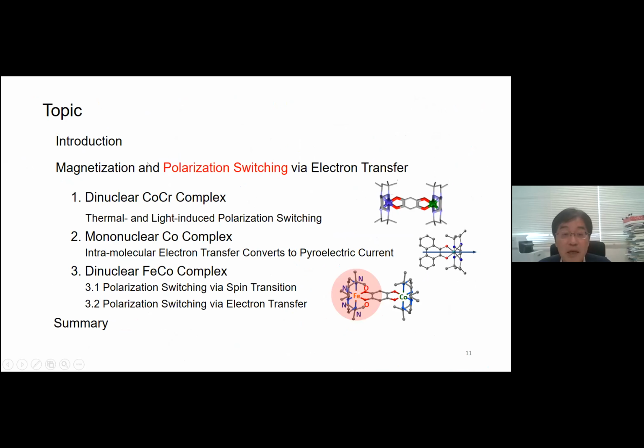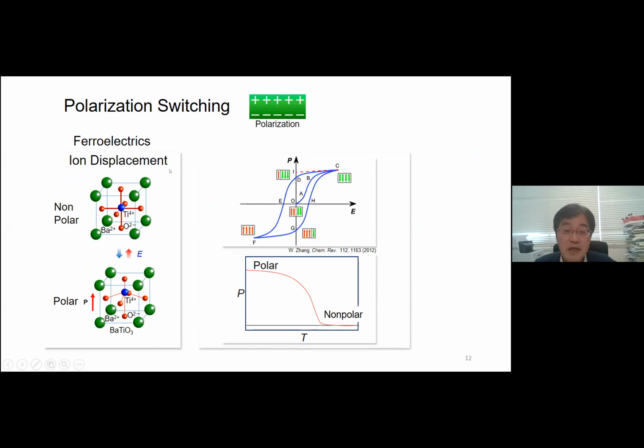And more recently, besides magnetization switching material, we are developing polarization switching material using electron transfer. So today I'm going to talk about 3 compounds: cobalt chromium dinuclear complex, cobalt complex, iron cobalt complex. They exhibit polarization switching. And the first topic is this polarization switching observed in this cobalt chromium complex. And as you know, polarization switching is observed in ferroelectric compound, and major mechanism is ion displacement. And its polarization can be controlled by electric field.